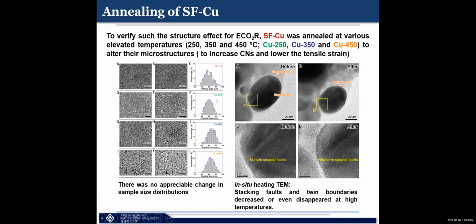So after annealing, basically we annealed at 250, 350, 450. The size distribution did not really change a lot. Basically the median is about 50 nanometers. Okay, so even after annealing, they are more or less the same. But for the stacking fault, we can see the density actually reduces after annealing. So the as-deposited film has a higher concentration of these stacking faults or step facets, and also a smaller coordination number, okay, for the copper surface.